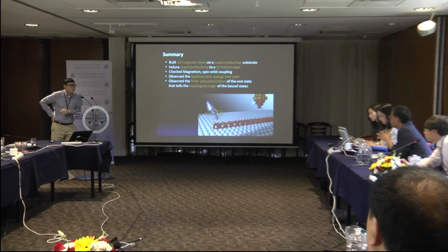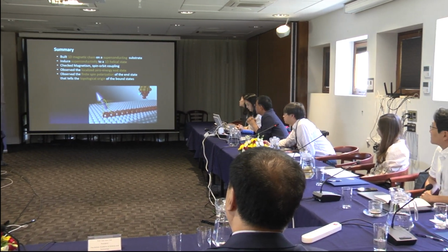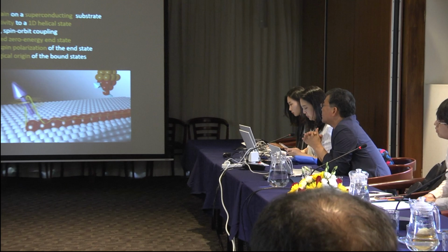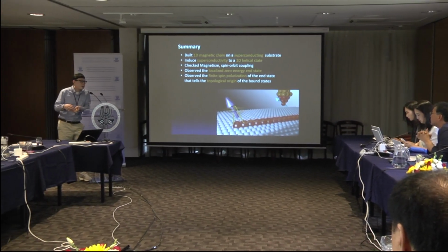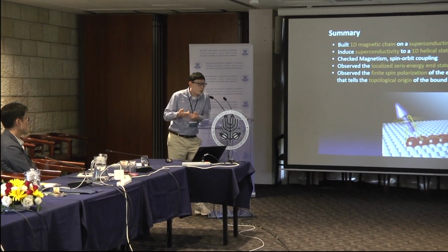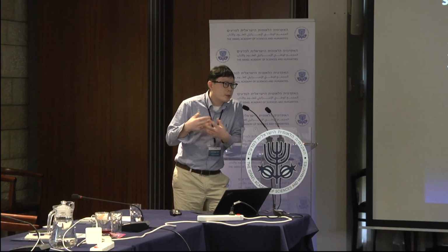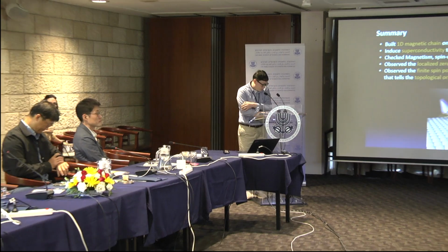I have a very short question. I remember that if I have a Majorana zero mode, then the conductance is quantized. I know it's not a conclusive measure, but in your experiment, is the conductance similar to what's expected for the Majorana? Yeah, that's a good question. In nanowire systems, they measure the tunneling spectroscopy, and sometimes they measure the quantized states. But in STM measurement, it was very hard to get into this region. If you get the tip tunnel junction closer and closer to the sample, eventually it will break the junction. So we tried to get into that region, but experimentally it is not allowed, so we cannot get the quantized conductance.